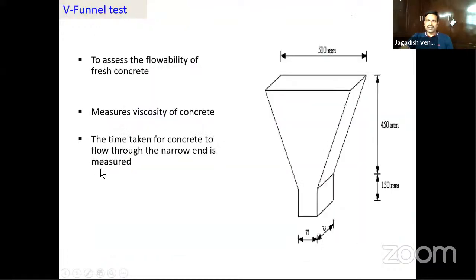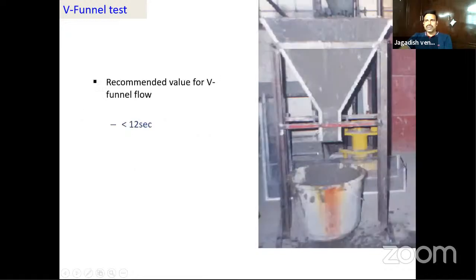Next test is the V-funnel test. These are the dimensions of the V-funnel. You assess the flowability of fresh concrete. Most of the time, with these V-type funnels, we measure the viscosity of fluids. You might have seen in chemistry, many of the viscous fluids, we measure the viscosity through V-funnels. You place the concrete in the V-funnel and measure the time taken for the concrete to flow through the narrow end. So that is the V-funnel time. The recommended values are between 8 to 12 seconds, 3 to 12 seconds, basically.